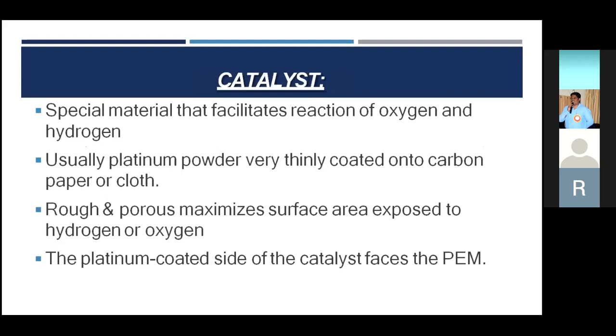Catalyst is a special material that facilitates the reaction of oxygen and hydrogen. Usually, platinum powder very thinly coated onto carbon or cloth is called catalyst. It is rough and porous, maximizing the surface area and exposing it to hydrogen and oxygen. So the platinum-coated side of the catalyst faces the PEM.